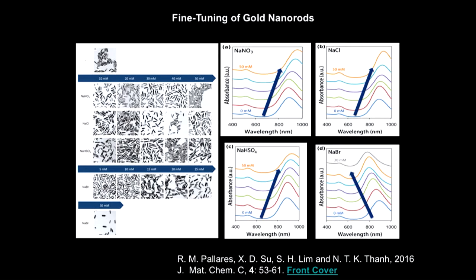So the most recent work is just the gold nanorod. As you can see from the TEM here, they are very homogeneous in shape. All of them have a rod shape. But remarkably, you can fine-tune the aspect ratio. At the longer near infrared, they absorb light very strongly. And that's one of the applications: you can use a laser light to heat up the gold nanorod and kill the cancer cell locally. Like in the video we're talking about magnetic hyperthermia cancer treatment, but you can also use a laser light to heat up the nanorod for cancer treatment.